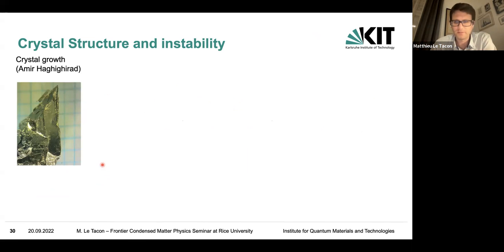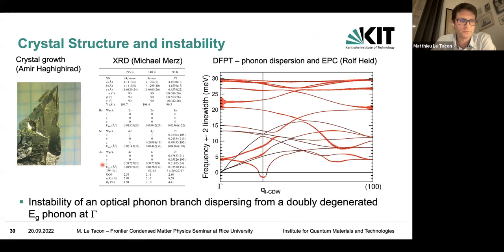In the previous version of that talk, this was inverted. So what we did is, the systematic way we do that is that we first have nice crystals. Then Michael Merz makes a very detailed crystal structural refinement of those crystals, giving the experimental lattice parameter. Our colleague Rolf Heid calculates the dispersion of the phonon.